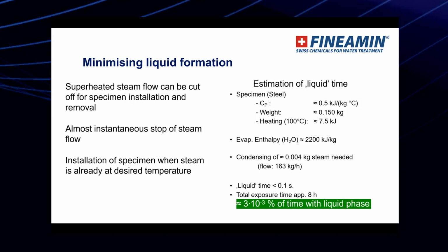But generally speaking, we try to calculate an estimation of the liquid time based on the heat capacity of the steel, which is 0.5 kilojoules, and then the weight of the specimens and the heating, and we measure around 7.5 kilojoules. And of course, the maximum period of a wet phase can be achieved when all heating energy for the specimen is taken from the condensation of steam.